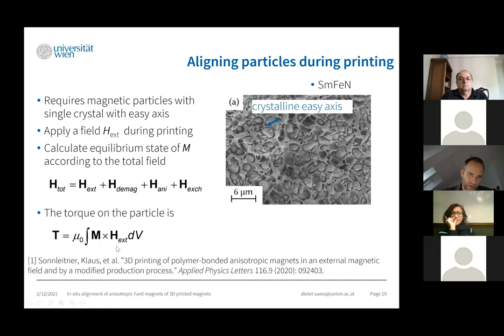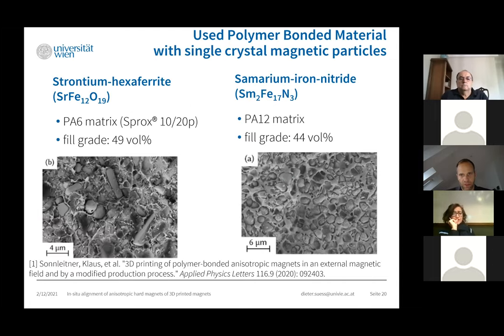H here is now the external field. The only important thing is M is the equilibrium position. If for example we have a perfect soft magnet, M is always pointing parallel to the external field, and then you can't produce a torque. So you really need, for example, an anisotropy to be able to align the magnetic particles during printing.